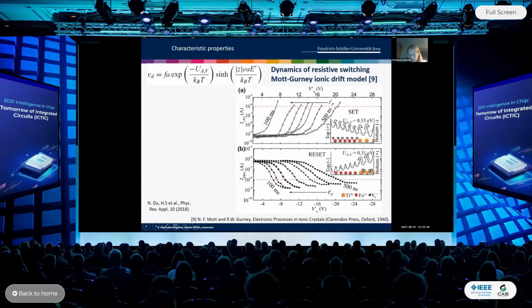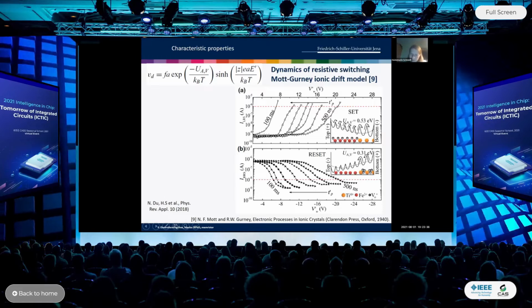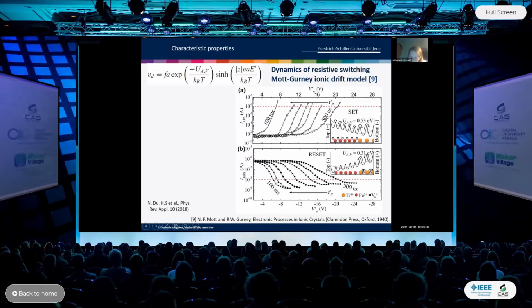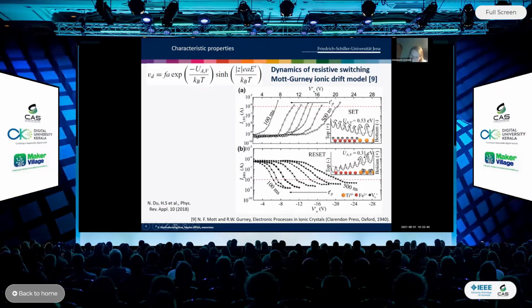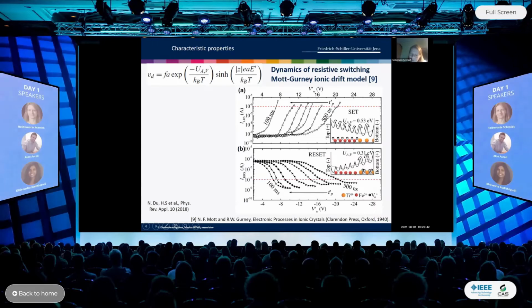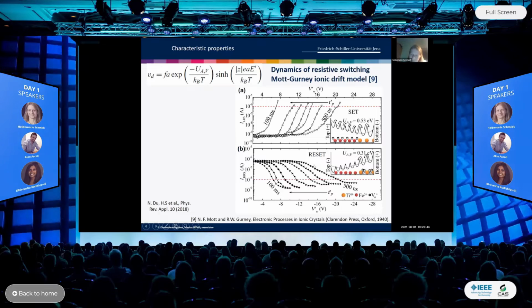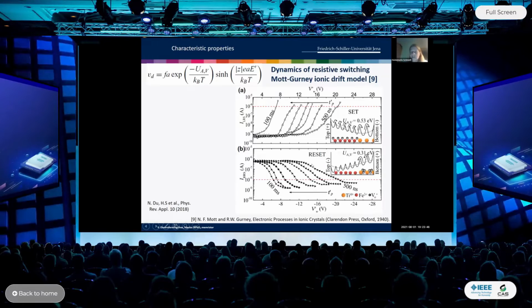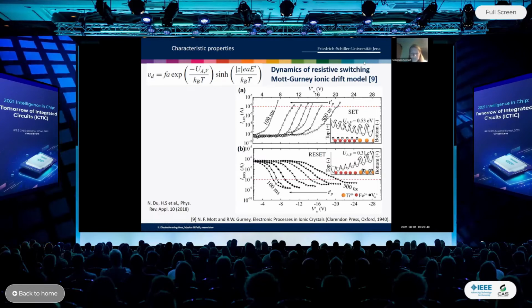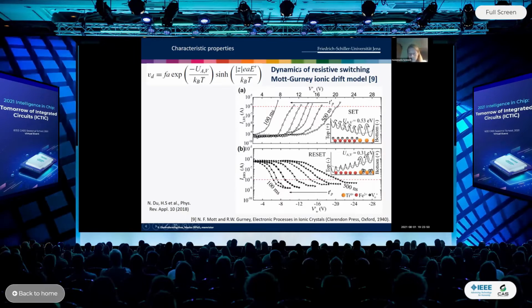And there's another possibility. If we apply a negative writing bias to the top electrode, then the oxygen vacancies have to drift from the bottom to the top electrode. And also there's a barrier height for this process, and there are dynamics in it. Okay. And then we modeled everything.